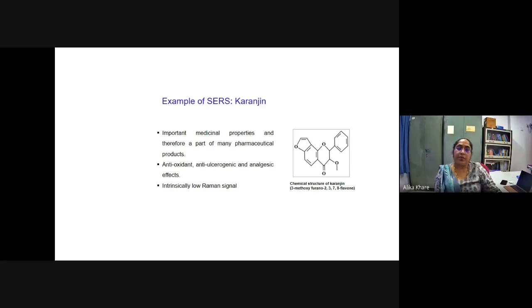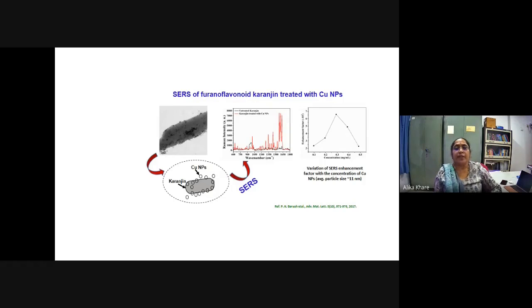This molecule is known for extremely low Raman signal. It was hardly detectable, but another colleague from chemistry did the DFT calculation and showed that the Raman spectrum is there, but the signal was very weak. So what we did was coat the crystal with copper as well as silver. Here I am showing the copper, and we did it with silver too. With silver, in fact, we got a better result.